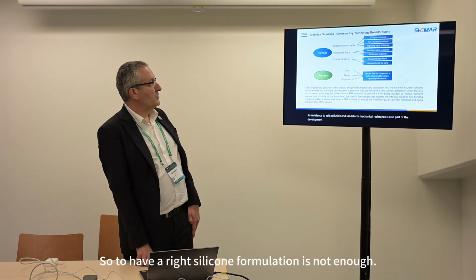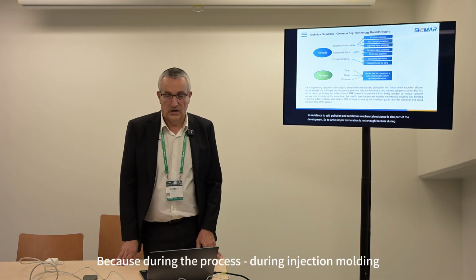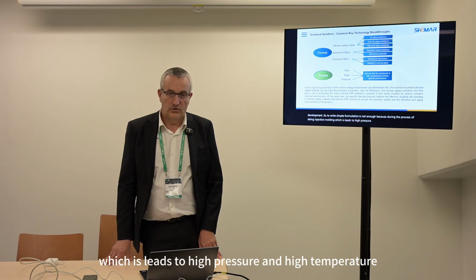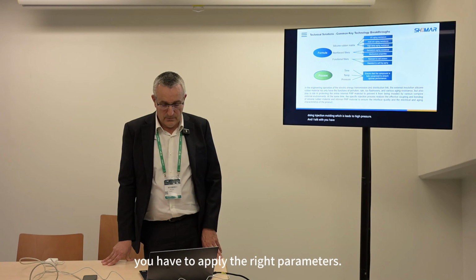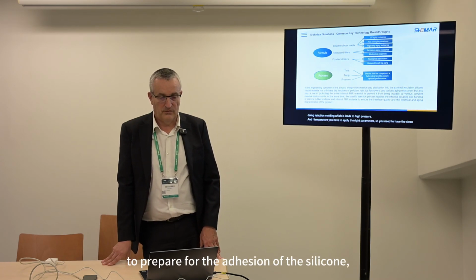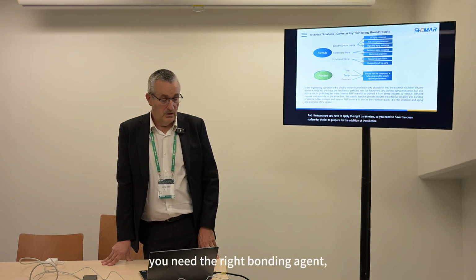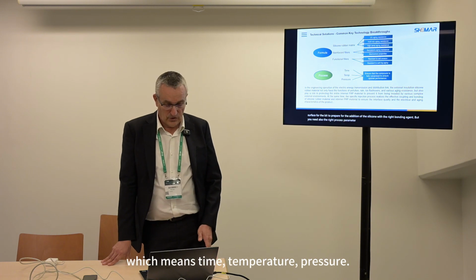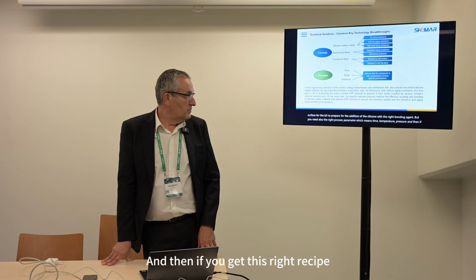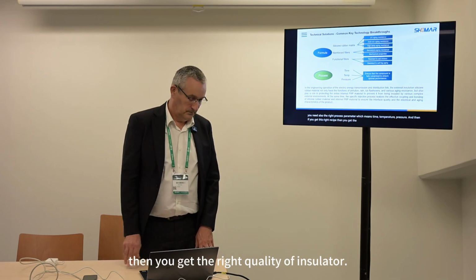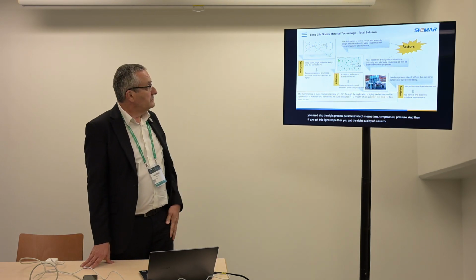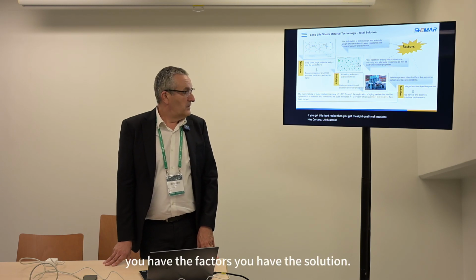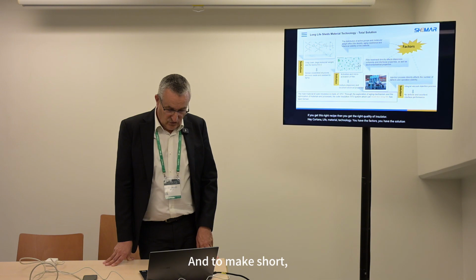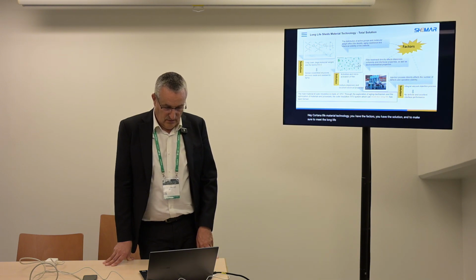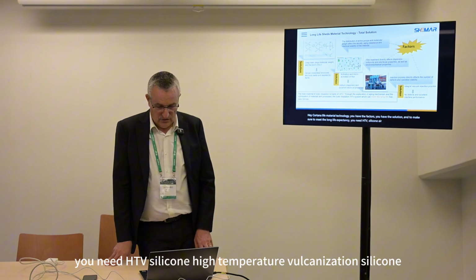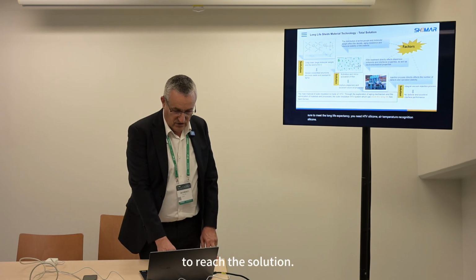So having the right silicone formulation is not enough, because during the process, during injection molding, which leads to high pressure and high temperature, you have to apply the right parameters. You need a clean surface prepared for the adhesion of the silicone. You need the right bonding agent, but you also need the right process parameters, which means time, temperature, pressure, and then if you get this right recipe, you get the right quality of insulator. So for long life material technology, you have the factors, you have the solution, and to make it short, to meet the long life expectancy, you need HTV silicone, high temperature vulcanization silicone, to reach the solution.